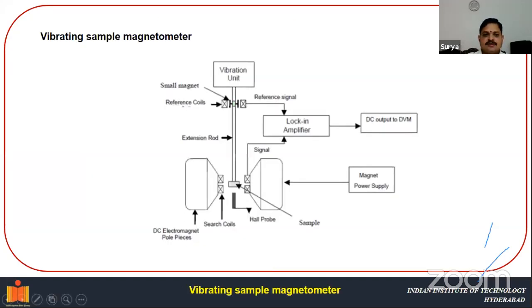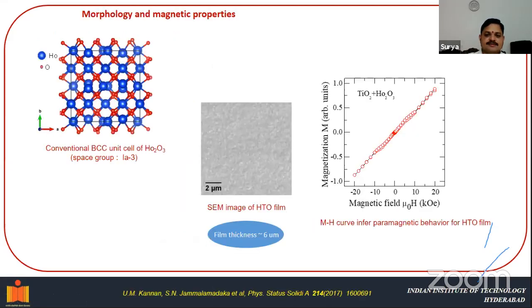Okay, we also used a technique called vibrating sample magnetometer to detect the magnetic moment of the sample. It works based upon Faraday's induction law. Whenever there is a flux change, there will be an induced EMF in the pickup coils. This EMF is proportional to the magnetic moment of the sample. Using the vibrating sample magnetometer, we also tried to analyze the magnetic properties of the holmium oxide. This is the magnetic field versus magnetization graph that we have obtained for the HTO film, the holmium doped or holmium added titanium dioxide film. It actually shows paramagnetic behavior.